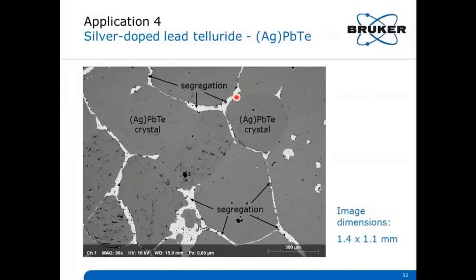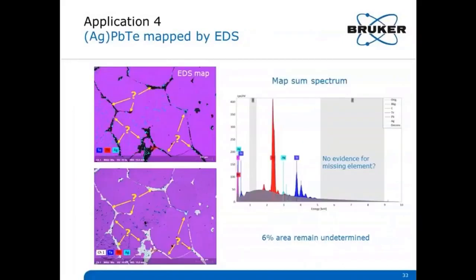The crystals are surrounded by a broad segregation phase. Here you see the segregation phase with a high density, obviously. Here are the results from EDS mapping with automatic element identification. Lead in red, tellurium in blue, and silver in light blue are readily identified in the sample.